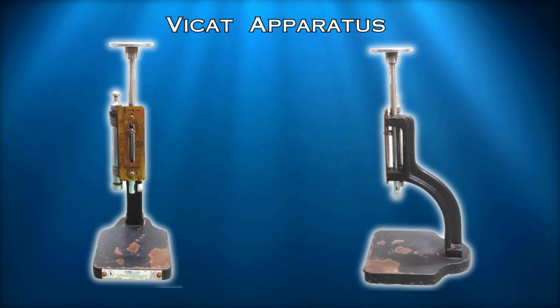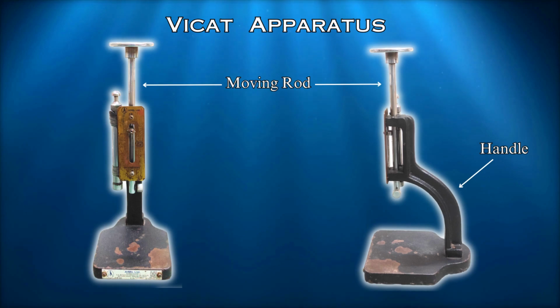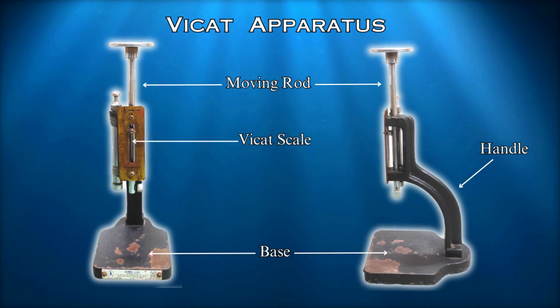It is used for the consistency test of cement, and includes components such as a handle, a moving rod with a weight, a base, a Vicat scale, and a needle. This apparatus conforms to Indian Standard Code 5513, with a standard weight of the moving accessory being 300 gram, plus or minus 1 gram. After attaching the needle, there should be a vertical clearance of approximately 50 millimeters, and the scale must have markings of at least 0 to 50 millimeters.